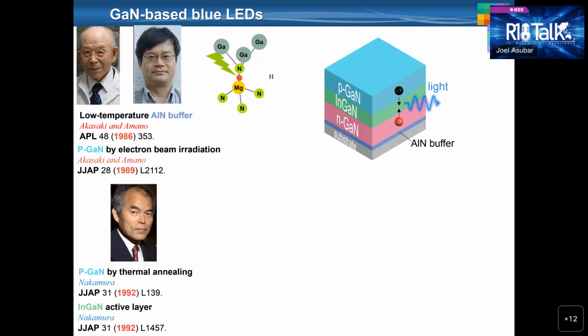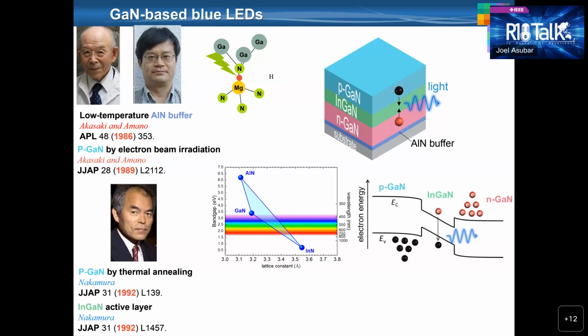Not only that, he also demonstrated the first P-GaN, InGaN or indium gallium nitride, N-GaN LED. For this LED, InGaN is inserted between the P and N-type GaN layers and serves as the active layer where the electrons coming from the N-type and holes coming from the P-type recombine. Note that the band gap of InGaN can be tuned, say, to 2.8 electron volts here, depending on the relative composition of indium and gallium.